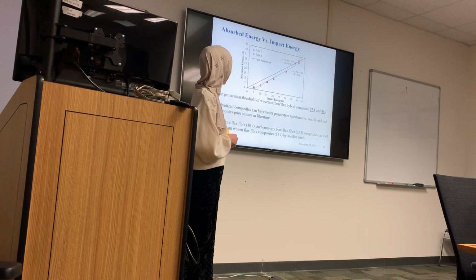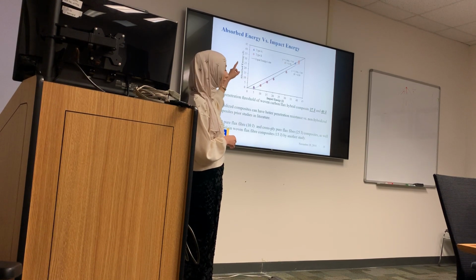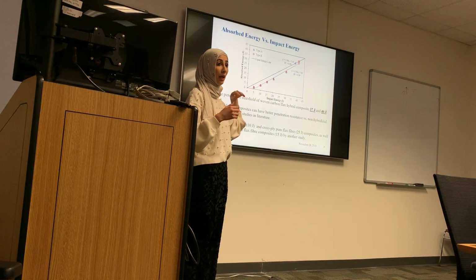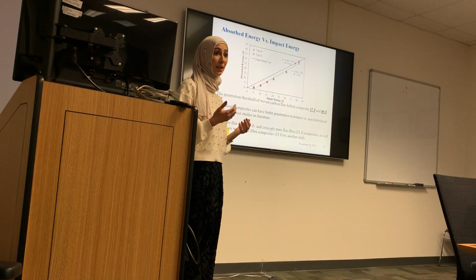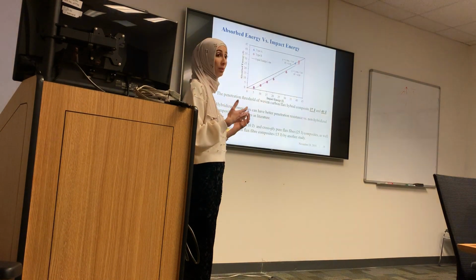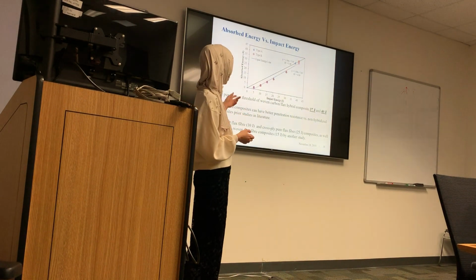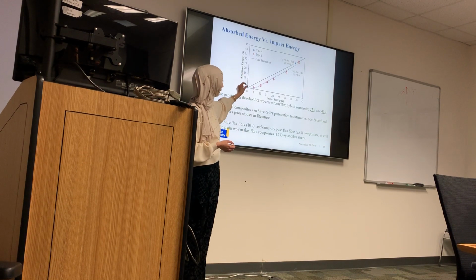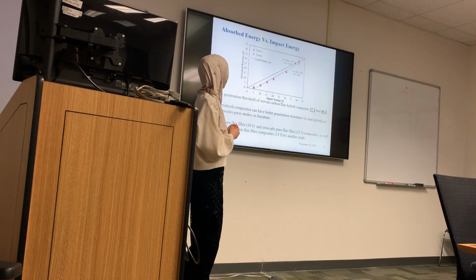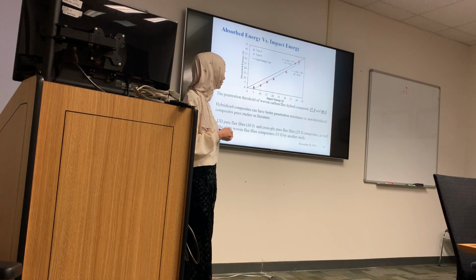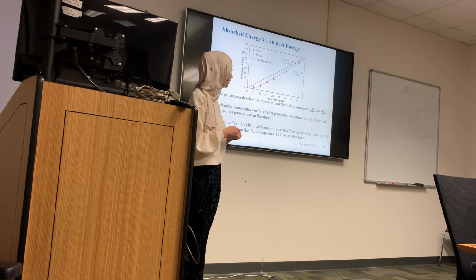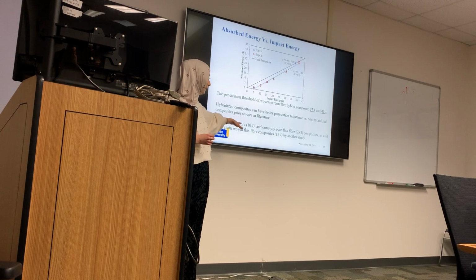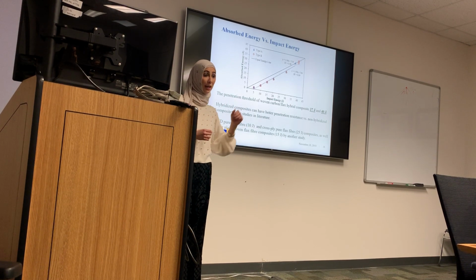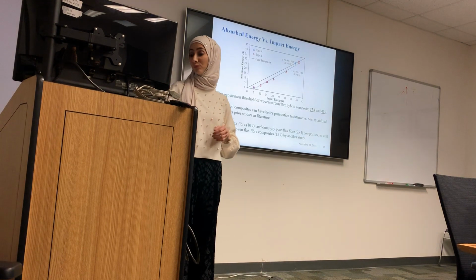We also could notice that there is overlapping between both composite types A and B. That's an indication that the majority of the load was carried by the carbon fiber, and a minor part was contributed by the flax fiber, because we see a little bit higher absorbed energy for type A. Type A shows a penetration energy of 37 joules. Type B shows a penetration energy of 40 joules. That was also compared to what's in the literature for pure flax. We see 10 for unidirectional, and for angle ply it is 25 joules.